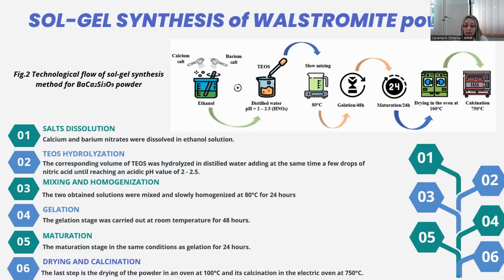So the first step in my work was to synthesize the walstromite compound by sol gel synthesis, following the steps that you can see on the slide. First, we did the salt dissolution using calcium and barium nitrates. And in parallel, we did the hydrolyzation of TEOS, which is an organic precursor for silicon. We mixed and homogenized these two solutions at 80 Celsius degrees for 24 hours until a sol was obtained. And then the steps of gelation and maturation were carried out at room temperature. And the last step was to dry the powder and calcinate it at 750 Celsius degrees.